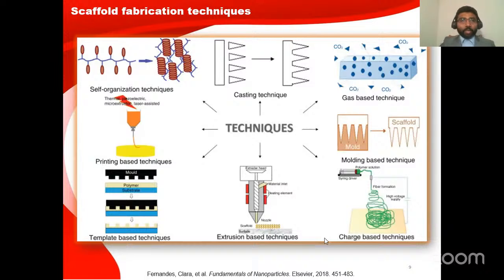There are several scaffold fabrication methods. For instance, we can use self-organization techniques like biomolecular organization approaches to make porous materials, and also casting techniques. We can make a porous mold. Then in this mold we can pour the polymer solution and make scaffolds. Then we can also incorporate various additives like porogens. Porogens can be salt-based porogens, and also carbon dioxide generating kinds of materials. Such materials can be used so that the carbon dioxide will be released during the processing. Then when the carbon dioxide is released from within the polymer, the way the carbon dioxide moves out will create porosities.